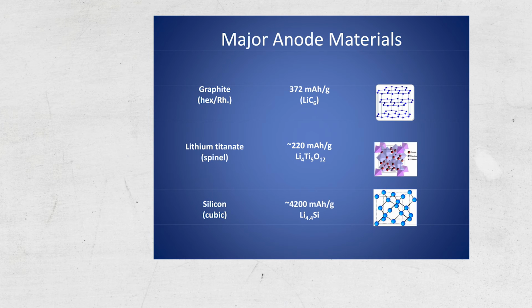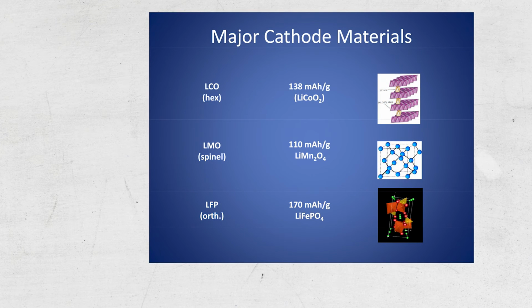This is what you find now in a lithium-ion battery. The cathodes: the historical cathode that was developed by John Goodenough, lithium cobalt oxide, has a hexagonal structure where lithium is intercalated between two slabs of cobalt oxide. Basically the slabs glide, and then they expand or contract according to the amount of lithium between the layers. And this process can be repeated many times because the CoO2 slab is very, very stable.